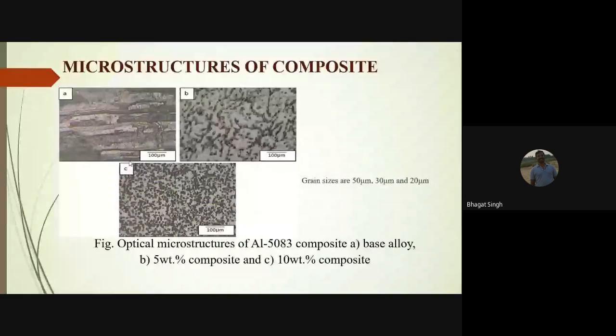Then we started with the microsection analysis, because this is where you can see whether any action has taken place by the addition of basalt powder. We can see here the base material has coarse grains, but once we add 5% of basalt powder, you can see the grains have been refined very much. In the initial microstructure the grain size is only 50 micrometer, and as you keep increasing the basalt powder, the grain size is reduced, and you can see fine grains of 30 micrometer and 20 micrometer with the addition of basalt powder 5% and 10% respectively. So what we expected has been achieved.